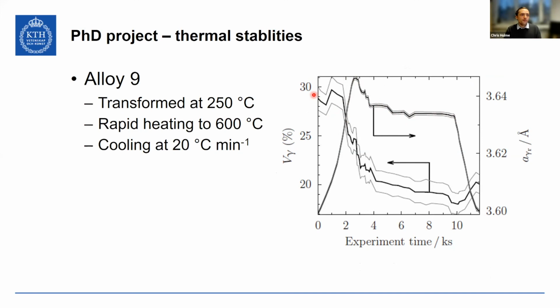So it's dropped from 29 plus or minus 1%, and it falls to roughly 19%, and it stays there. And the lattice parameter initially undergoes thermal expansion, undergoes a slight contraction as it loses a lot of carbon, and then contracts under cooling. But look at the austenite under cooling, it's still stable, it doesn't go anywhere. So that's a very positive step forward, that now we can survive quite an aggressive tempering treatment, certainly more heat than Rolls-Royce would normally expect to see in that particular component.